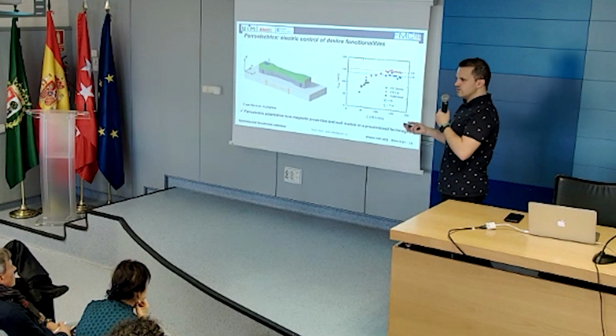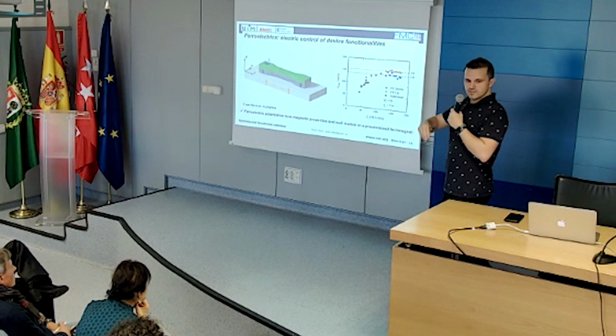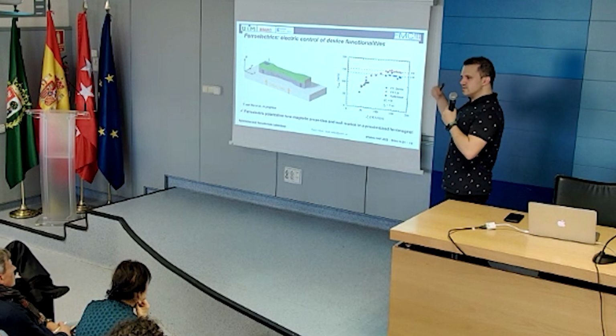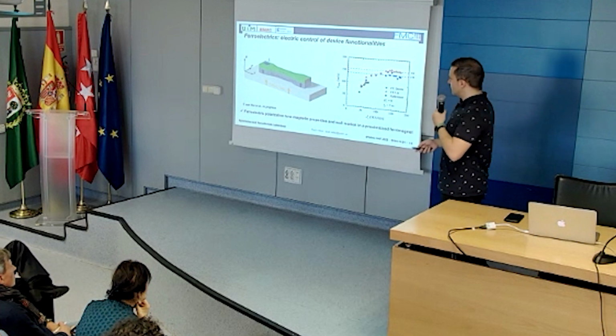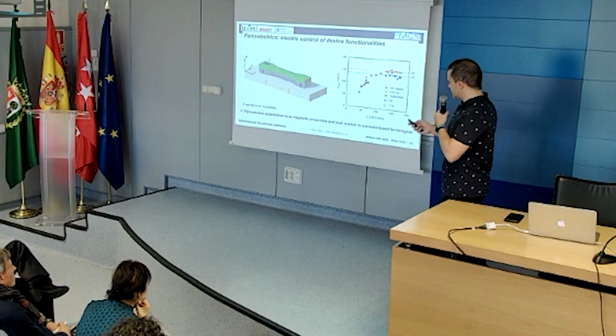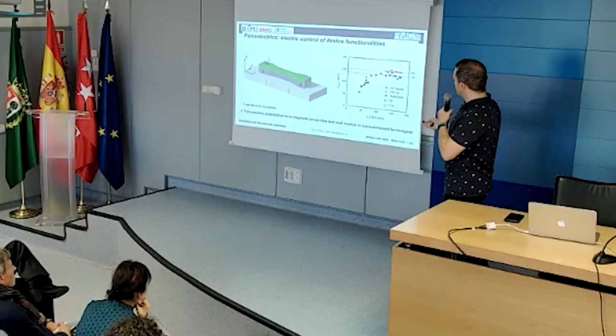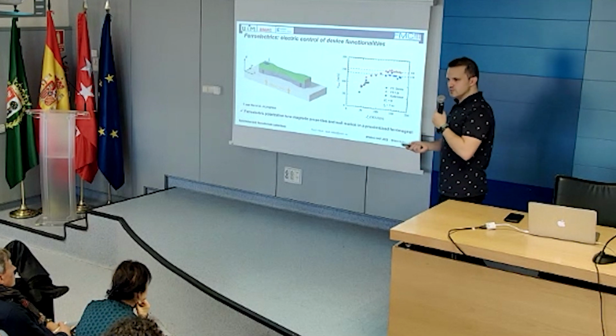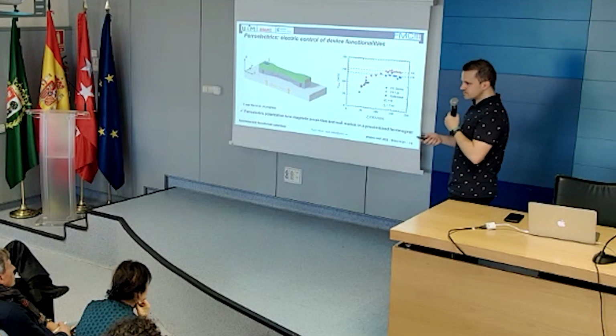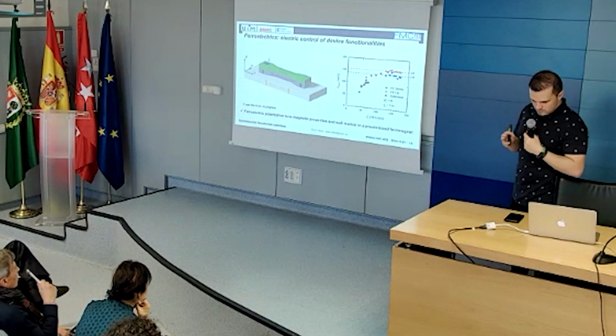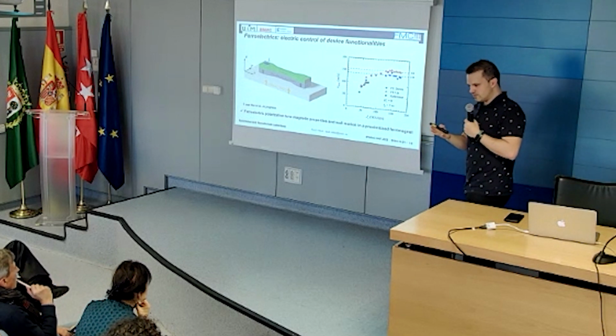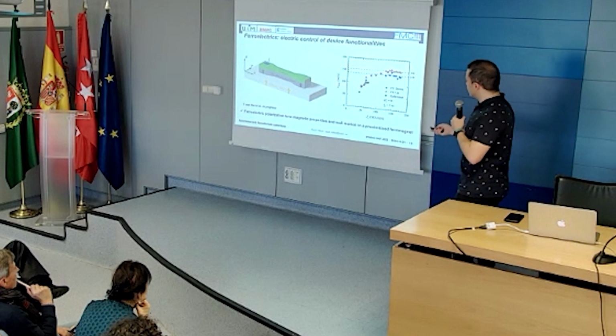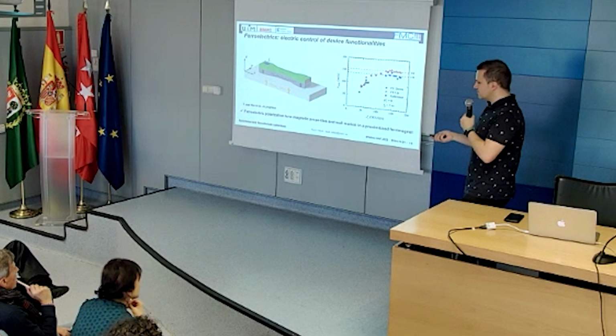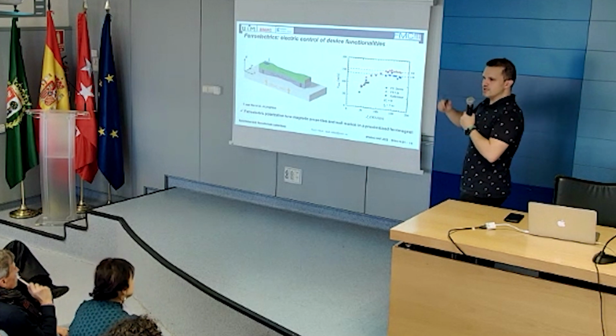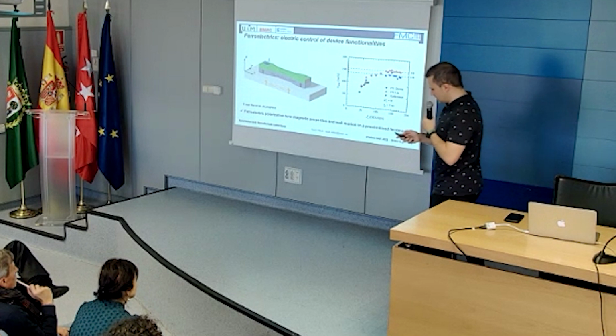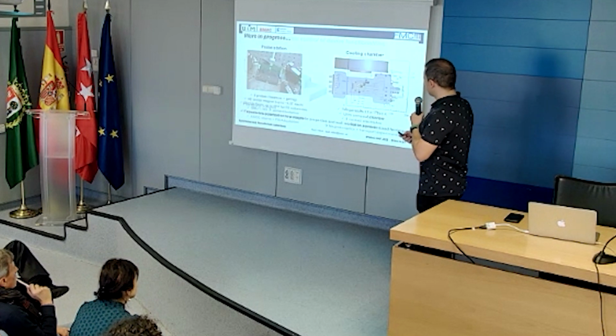And the interesting thing here is that if you remove the electric field, you retain this polarization, so you have a non-volatile change in the properties of the system. What we see is that we are changing the velocity of the domain walls, which is related to this interfacial interaction that leads to the stabilization of the chiral domain walls. So you have the Dzyaloshinskii-Moriya interaction that you are tuning by the ferroelectric polarization. That's the first realization of this type of experiments.